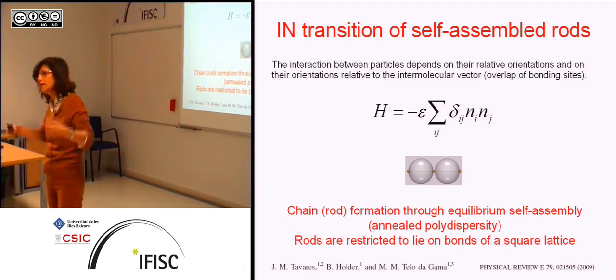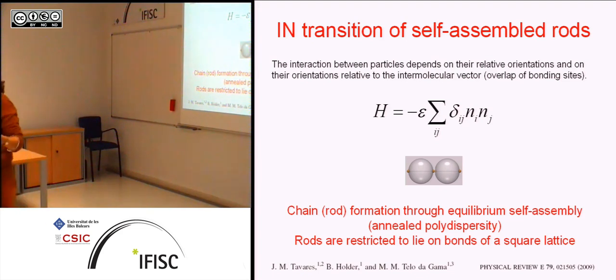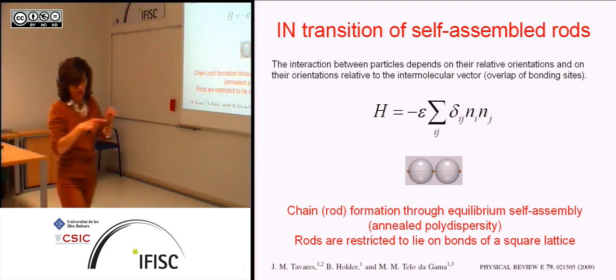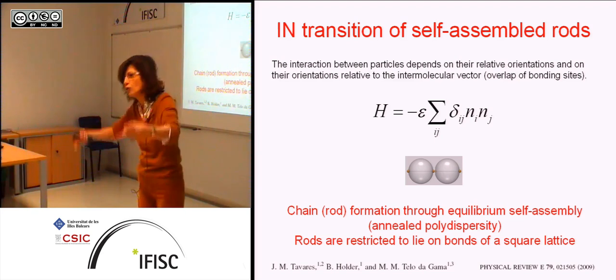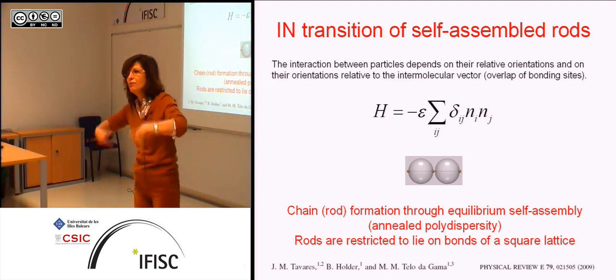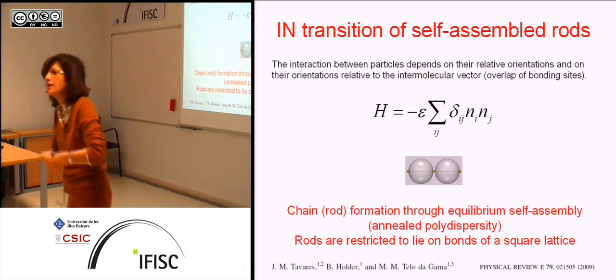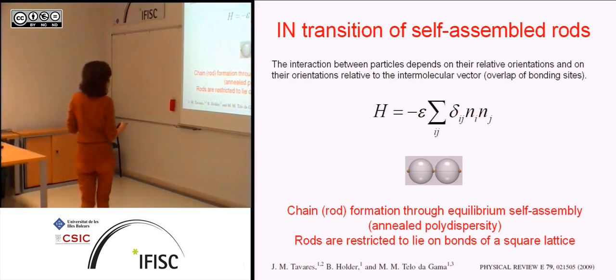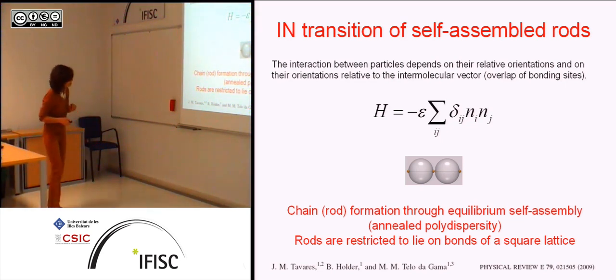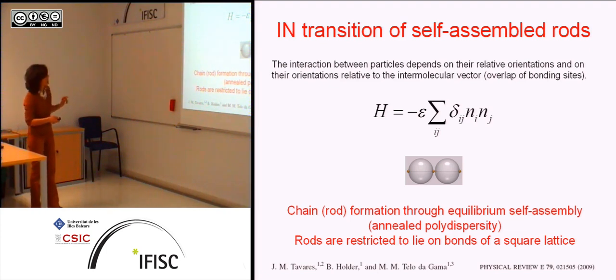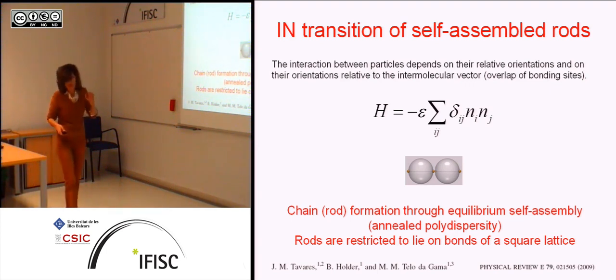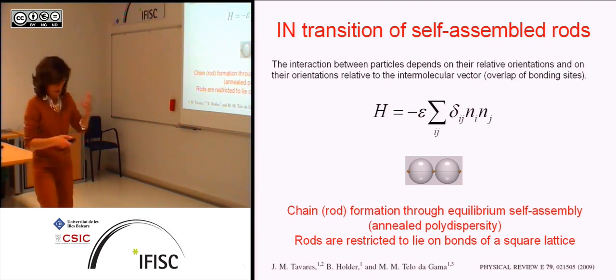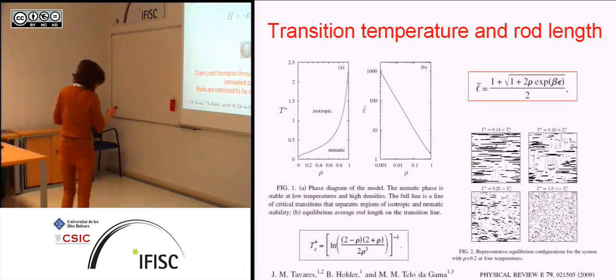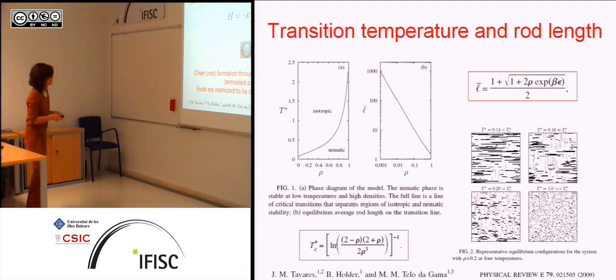Now there will be a length distribution, and if you let these things equilibrate, this length is like polydispersity, but it's not quenched. It's not prepared before you look at the experiment. It's actually driven by thermal fluctuations, and it's equilibrium. Okay? So this is the simplest model you can get. I'll put them on the square lattice as before, and the difference is that now I have polydispersity, and this polydispersity results from the equilibration, from the equilibrium process.